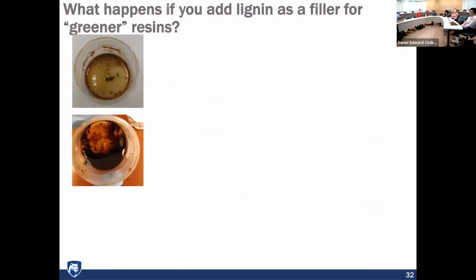And this is important, especially for lignin, because if you've ever seen lignin, you know that it's brown. And so you might think, well, now you're making a material that's relatively opaque. And so if you shine light on it, it's going to be difficult to polymerize. So when we first started doing these photopolymerization reactions, we said, well, let's just take our lignin that we upgraded and dump it in and see what happens. And what you get are these heterogeneous samples. You can see that you have these resins with these little chunks. See the little chunks in there? That's lignin that doesn't dissolve.